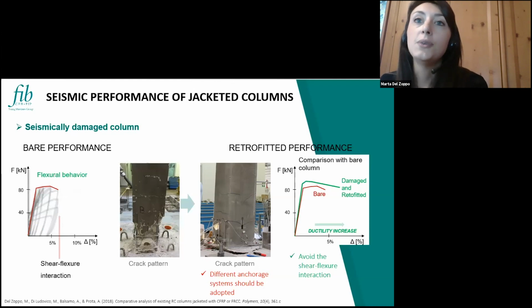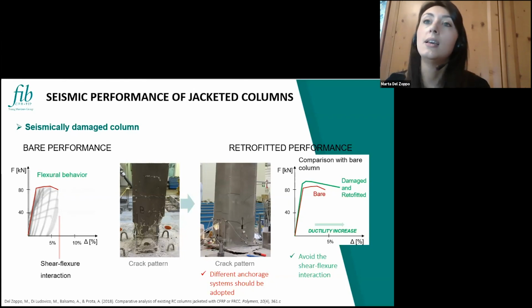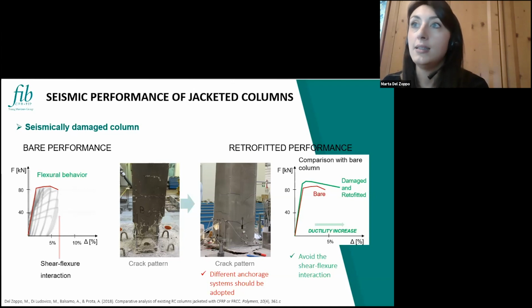But in general, if we compare the behavior of the damaged and retrofitted specimen with the behavior of the bare one, so the original one without any damage, we can see that we have a very, very good result in terms of recovery of the original capacity, and also we are avoiding the flexural shear interaction that we observed in the original specimen that limited the ductility.